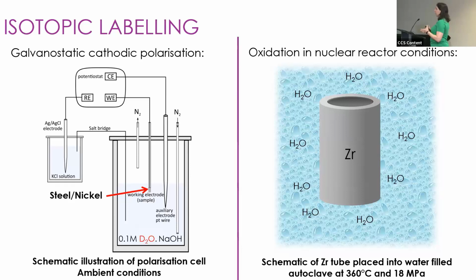And we grow that in normal water, first of all. After that specified time period, we'll take this zirconium tube out of that autoclave, place it into a different autoclave, this time containing water containing deuterium and also oxygen 18 in this case. And then we allow that oxide to grow for a further period of time.